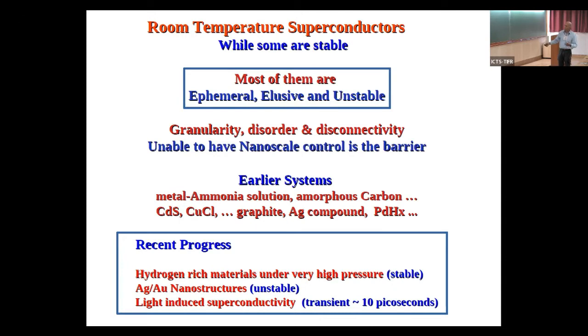Recently remarkable progress has taken place in hydrogen-rich materials under very high pressure, with stable superconductivity. Not far from here, at the Indian Institute of Science, Bangalore, Thapa Pandey, Arindam Ghosh, and collaborators have seen unstable superconductivity even at room temperature in an unexpected place, namely silver-gold nanostructures. When you take YBCO at room temperature, which is not superconducting, and shine light of a particular frequency, femtosecond laser pulses, it exhibits transient superconductivity lasting for 10 picoseconds. So to that extent it is stable.